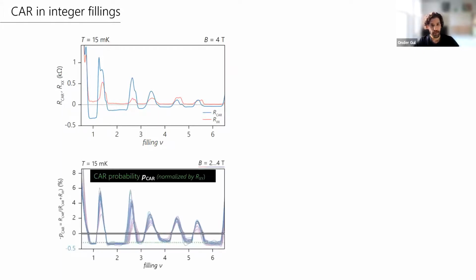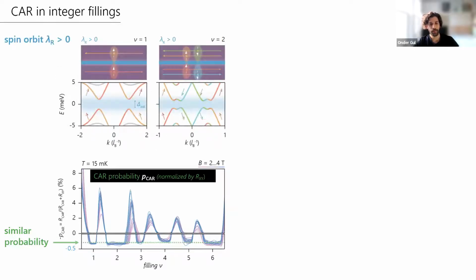We then normalize the CAR voltage for each filling by their Hall voltage and obtain CAR probability. We find similar probabilities for all integer fillings. This suggests presence of spin-orbit coupling, without which CAR is not possible in spin-polarized odd fillings. Carlo also mentioned this point. Basically, if you have spin polarization, the s-wave superconductor will not give you an Andreev reflection.